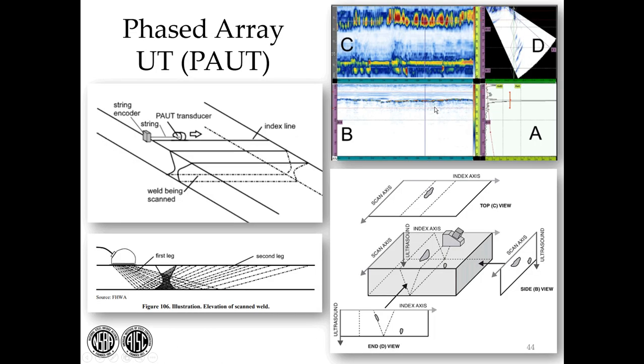But at this particular point, just to clarify, this is the sound that you see at that point. This is not a very good weld, a long defect, but it emphasizes the point. You can also use these views to help characterize, but the pass-fail of the joint is based on whether you have something spiking out of this gate.